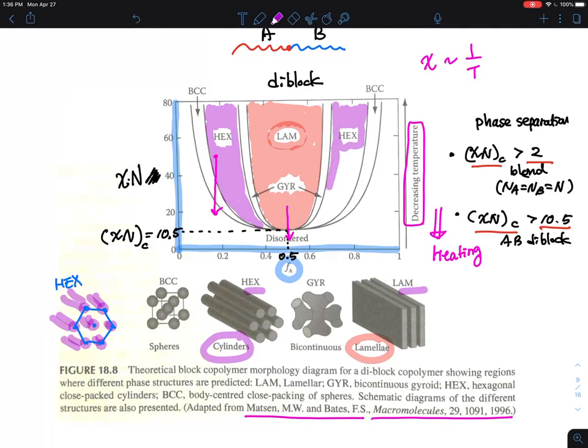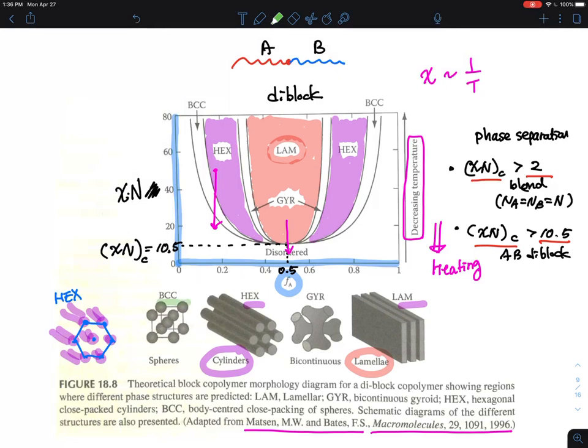You can see two-layer structures for the lamellar as two-dimensional building blocks and the more linear one-dimensional line-like structure which is cylinders in hexagonal packing. The hexagonal pack cylinder is about 30 percent composition here, and it is symmetric because this is a theoretical diagram.